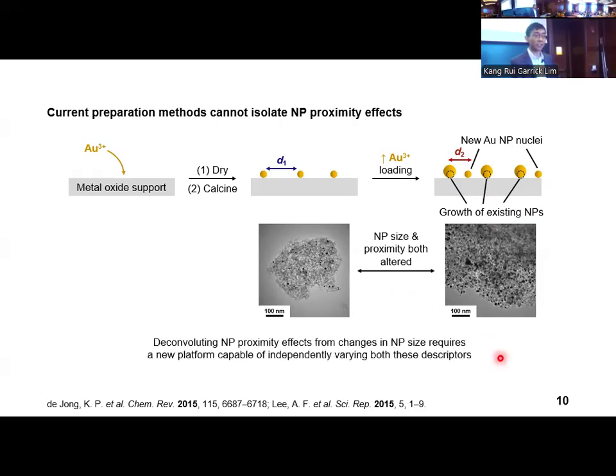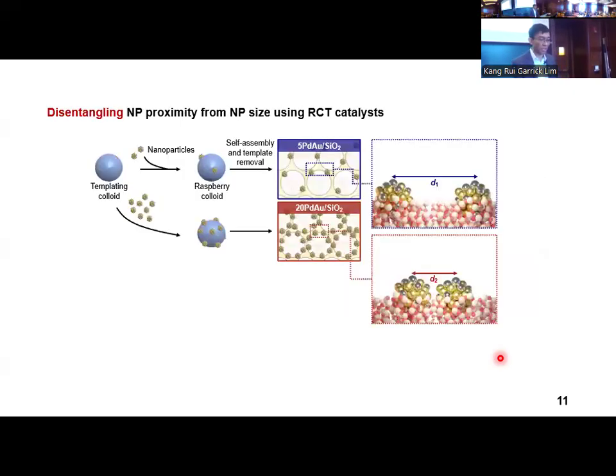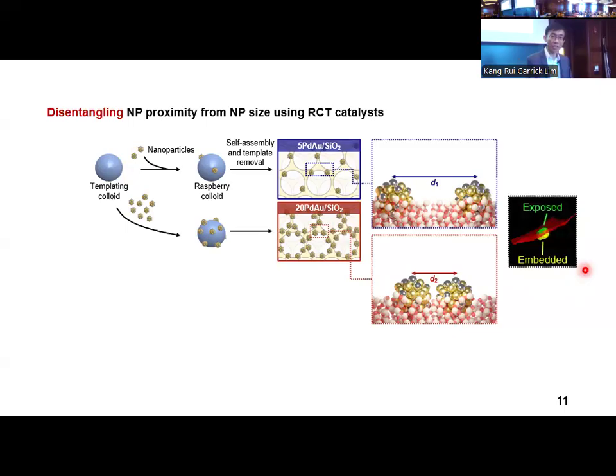Deconvoluting nanoparticle proximity effects from changes in nanoparticle size thus requires a different catalyst platform capable of independently varying both these potential descriptors. The RCT method allows us to fabricate a series of catalysts, in this case comprising palladium gold nanoparticles supported on silica, whose average interparticle distance was tuned by metal loading. As the ratio of the nanoparticles to templating colloid increases, the metal loading can be reliably increased from 5 to 20%, thereby reducing the interparticle distance at a fixed nanoparticle size. Additionally, the partial embedment of practically all the nanoparticles confers strong resistance against nanoparticle sintering during catalytic evaluation.